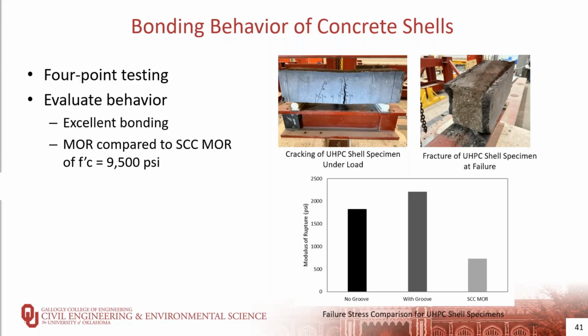The grooving in the shell did achieve a higher failure load, but with only two specimens, we can't make a solid conclusion, except that they both exceeded the expected strength for the composite specimen.